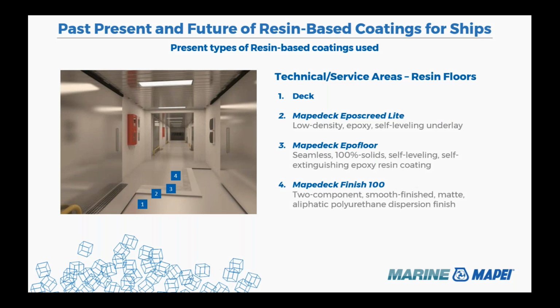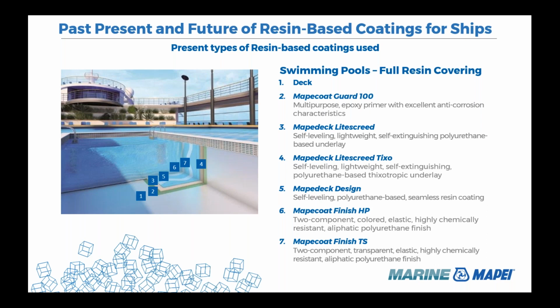This is another example of resin system we can find on board. In this case, this is one of the more complex systems because it is the resin system we apply on a pool trunk. The pool trunk is one of the most delicate areas on a ship, so it needs particular care. In this case, we apply the Mapecoat Guard 100, which is our adhesion primer and also has excellent anti-corrosion characteristics. We typically level the bottom of the floor with the Mapedeck Litescreed, which is the same polyurethane underlayment we explained before.